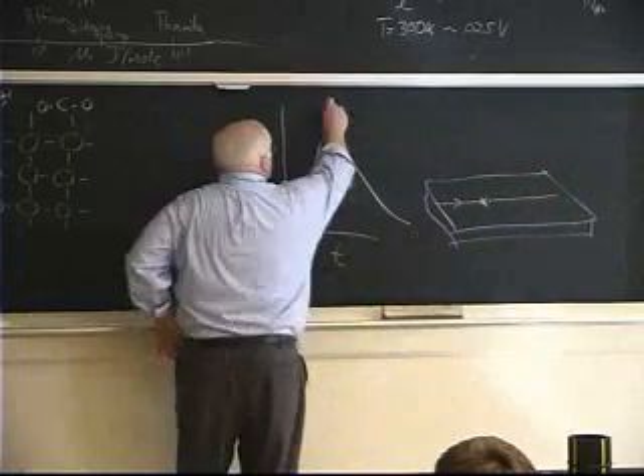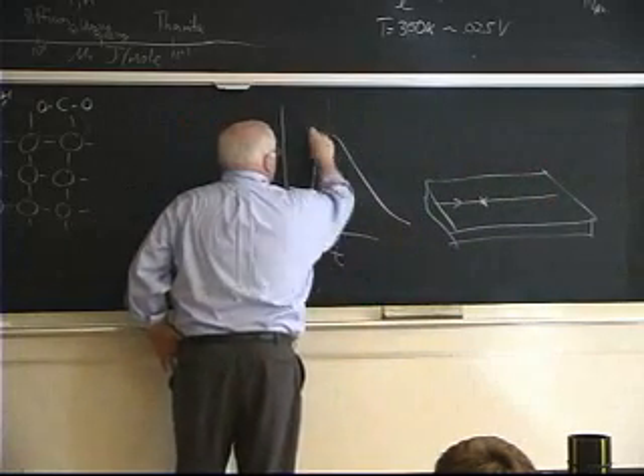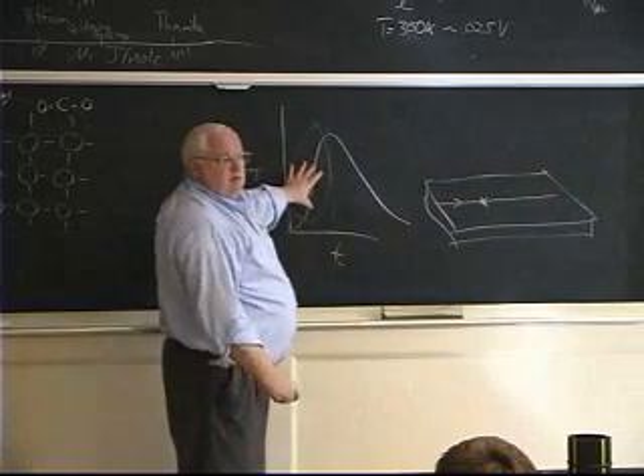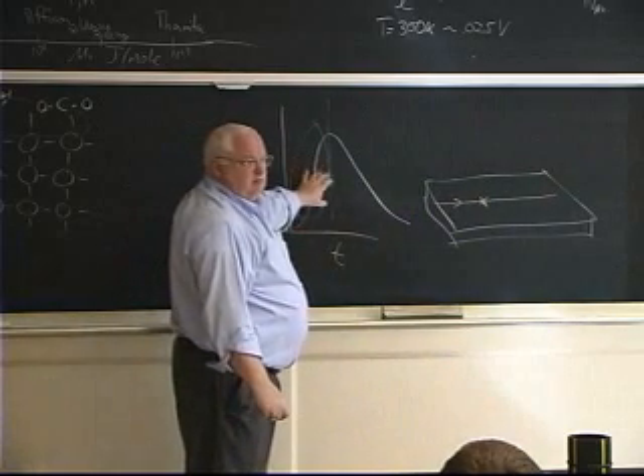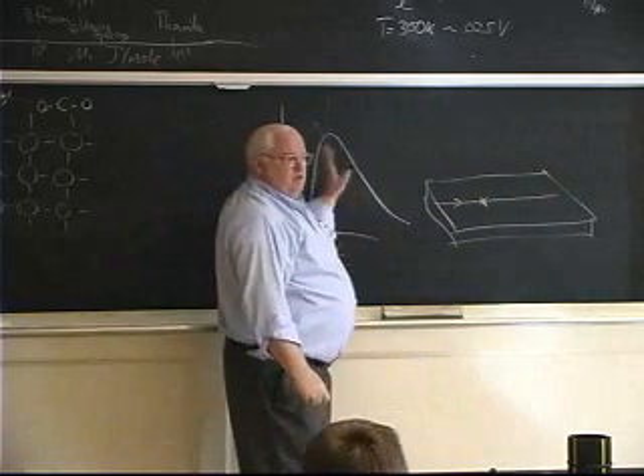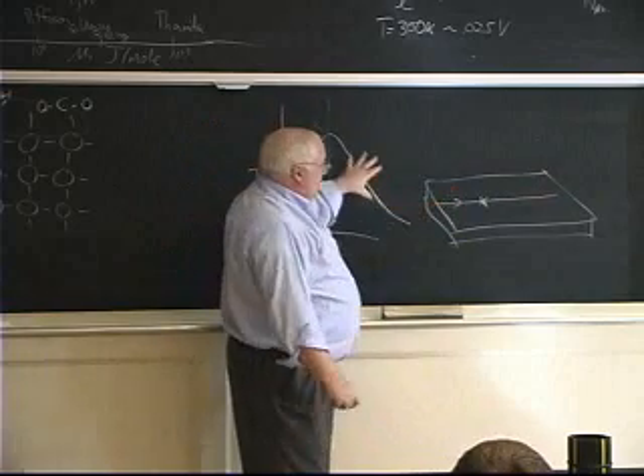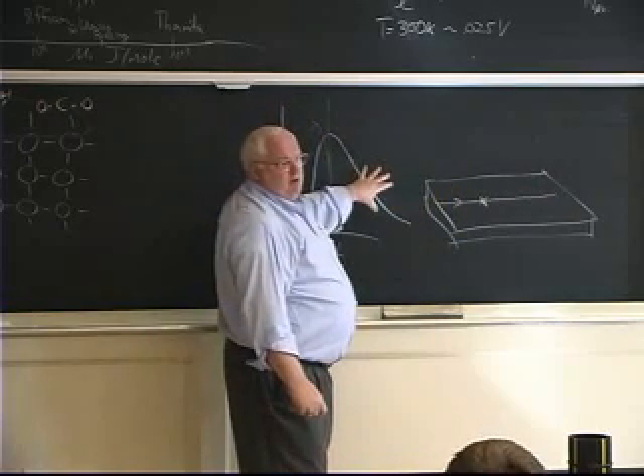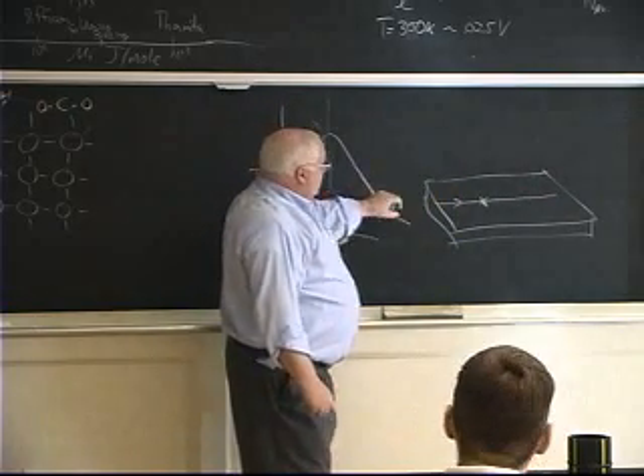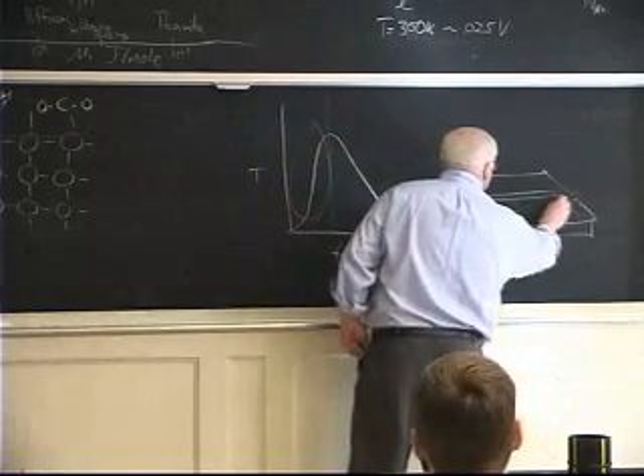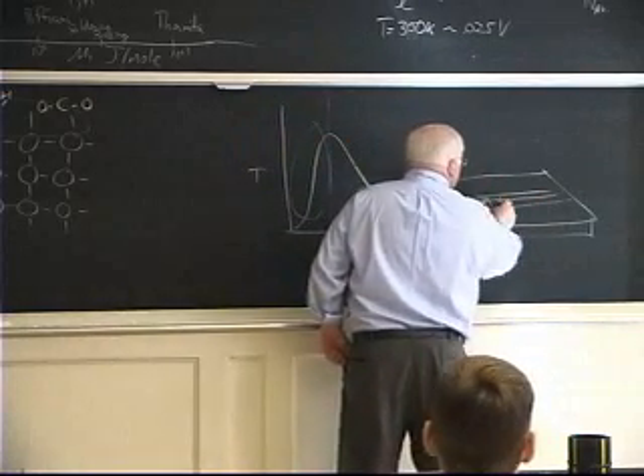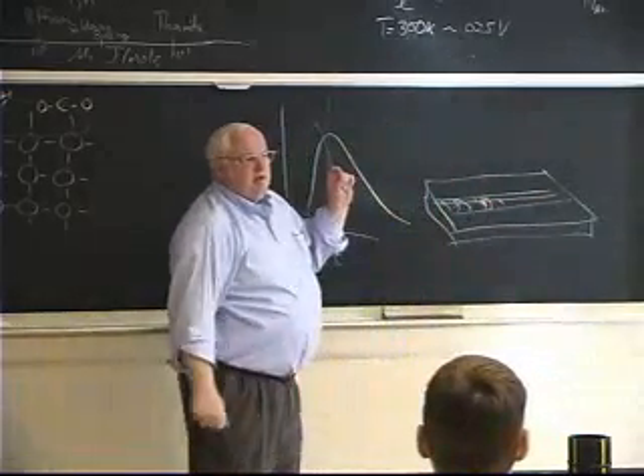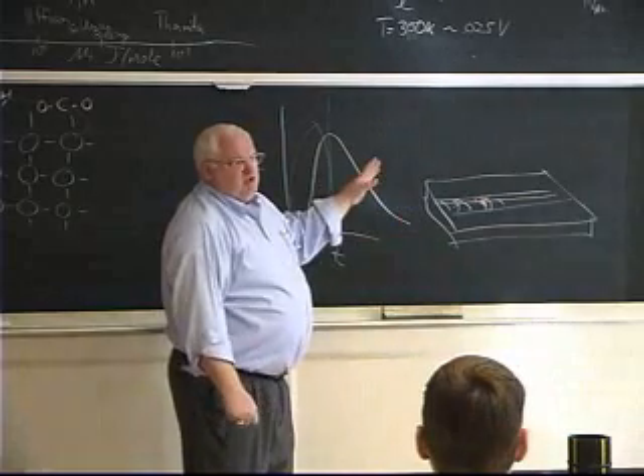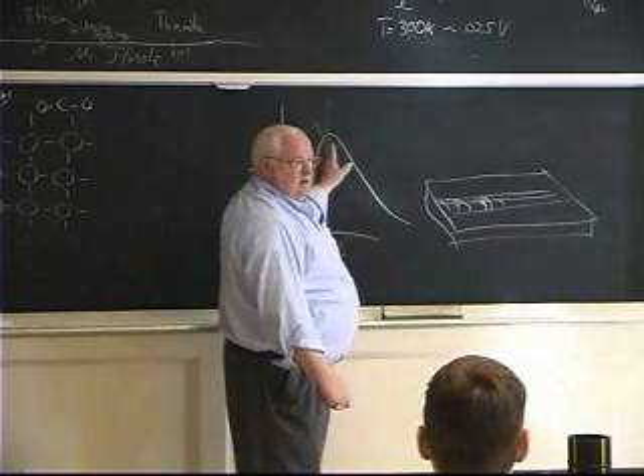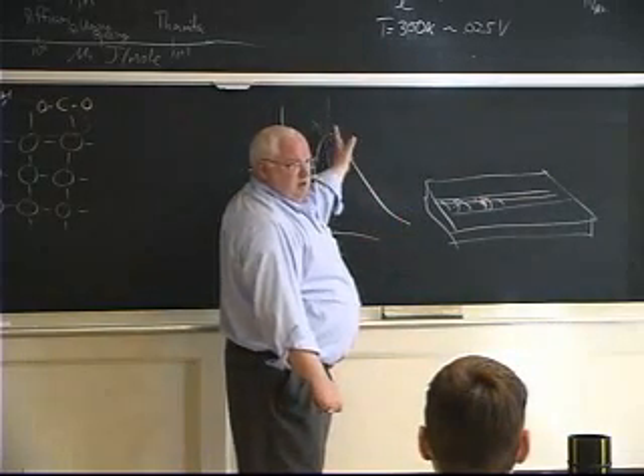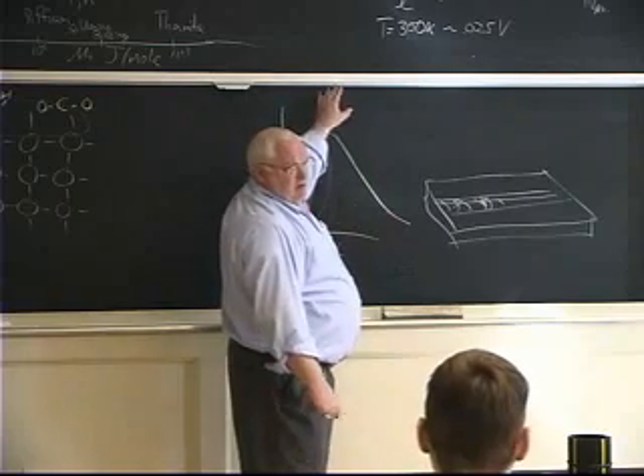It turns out for electroslag welds and arcs and other things, I form my heat affected zone on this heating part of the cycle. For lasers and electron beams, where I'm traveling much faster, I actually form the heat affected zone on the cooling part of the cycle. And so the width of the melted metal that I create ends up controlling the width of the heat affected zone, not the speed at which I heated it up. Because for very fast processes, it's the cooling time, not the heating time, that's important.